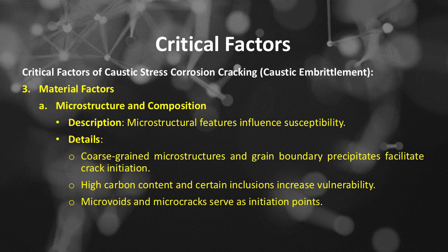Material factors of caustic embrittlement include number A, microstructure and composition. Description: microstructural features influence susceptibility. Details of microstructure and composition: critical factors include coarse-grained microstructures and grain boundary precipitates, which facilitate crack initiation. High carbon content and certain inclusions increase vulnerability. Microvoids and microcracks serve as initiation points.